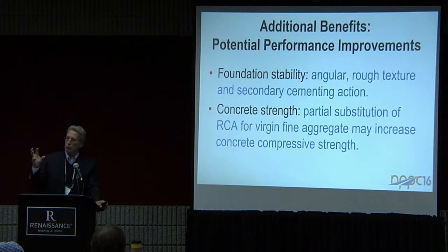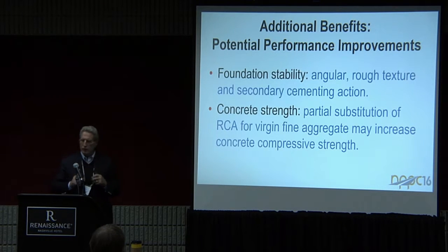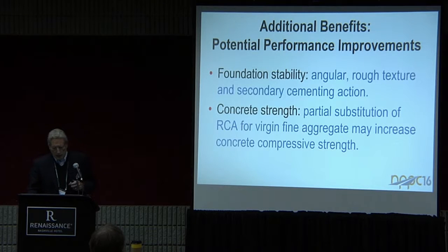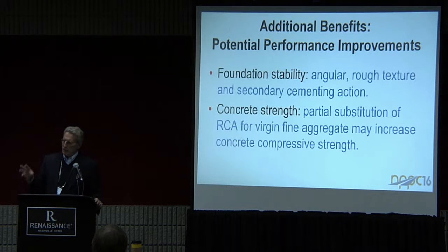You also have a very rough surface texture and an angular nature of the product, so you get very good grain interlock in that foundation as well. There have also been a few studies that have shown that when you use it back into concrete materials, particularly the fines, maybe not so much the coarse aggregate, limited amounts of concrete fines, maybe up to 20-25% replacement of fine aggregate, will actually improve the strength of the concrete.